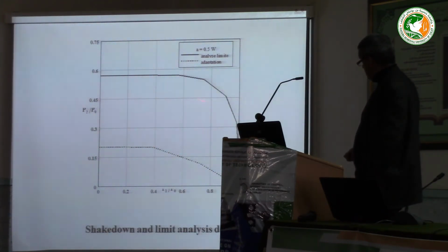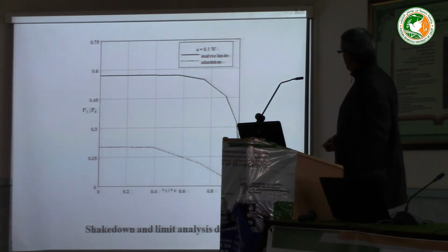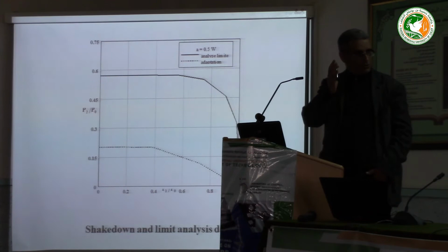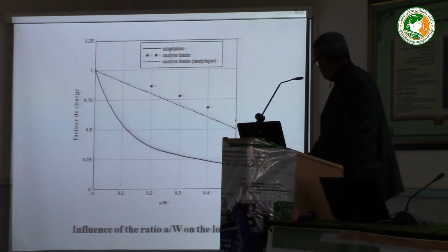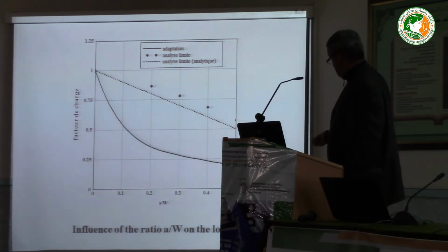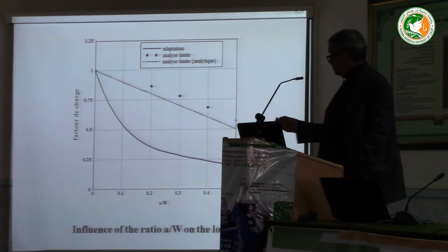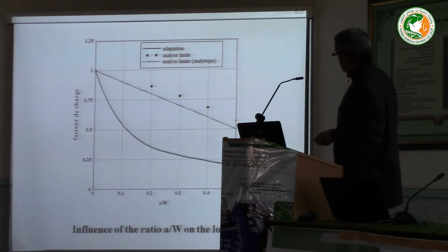Here is a comparison of the assessment for the limit analysis and the shakedown analysis for a crack length equal to half of the width of the plate. Here we have comparisons between shakedown, the limit analysis calculated with our program, and the analytic solution. Here we show the variation of this loading factor with the ratio between crack length and the width of the plate.